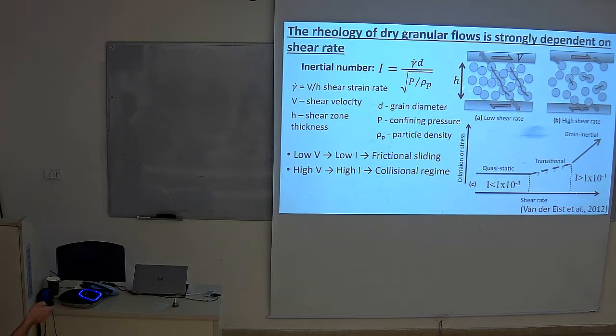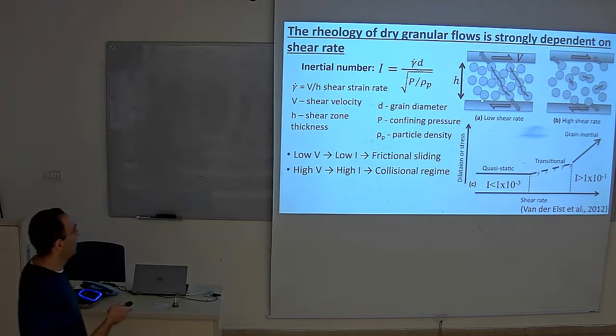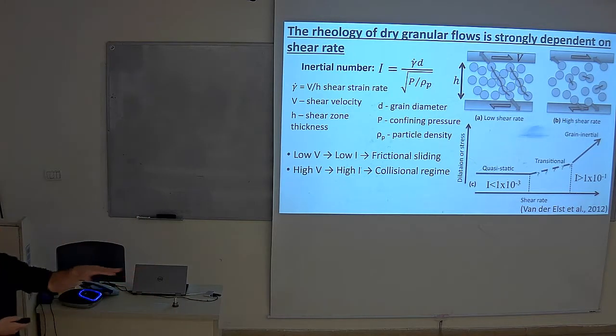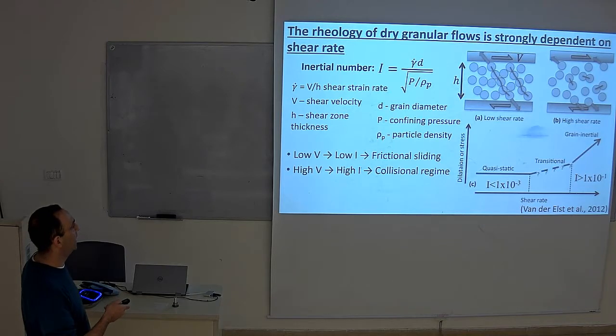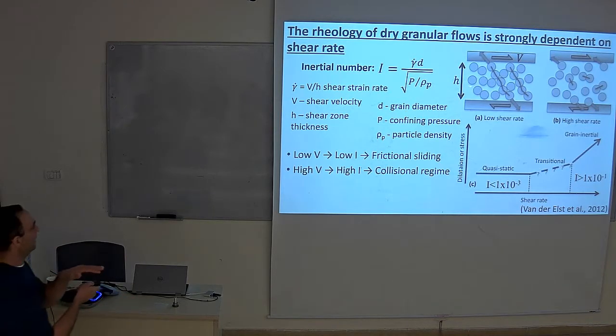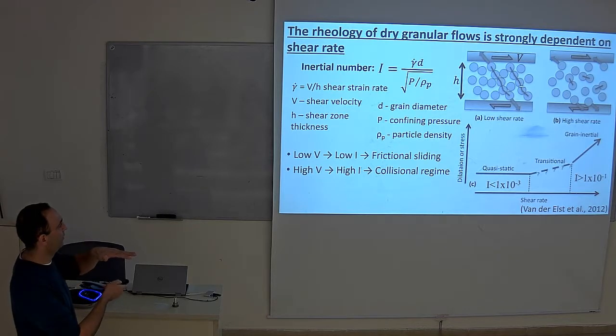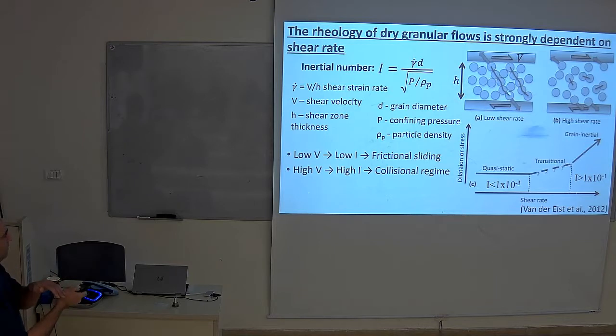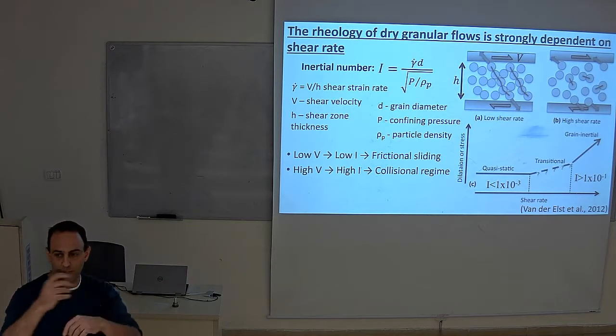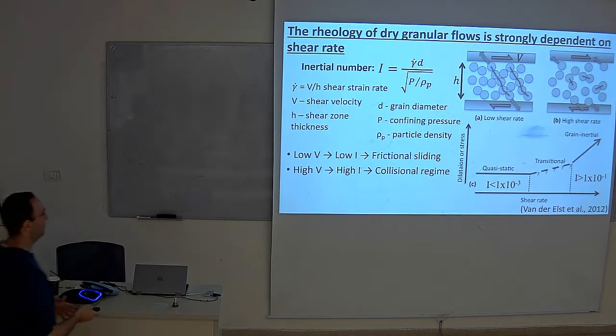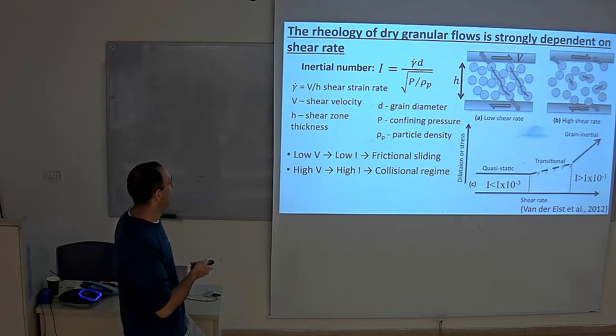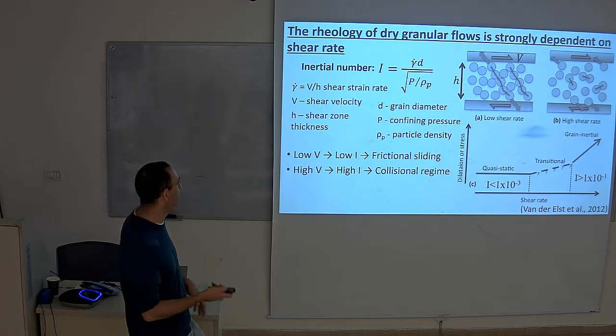So what we know is that granular material basically depends strongly on the way it is shearing. By that I mean that it can shear like a solid. It's a solid-like regime where most of the stress applied on the granular material is held by stress chains that are marked here by these lines. Differently, at higher velocities, and we'll talk about it immediately, there is gas-like behavior of the granular material. There are a lot of impacts between the grains, they are moving very fast, and they sometimes look like an ideal gas.